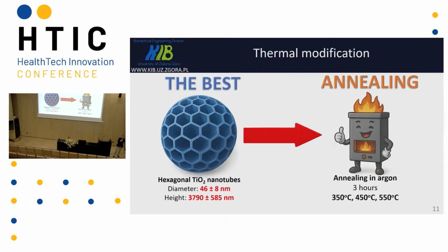I told you that we had to use a thermal modification process. Why? There are a few reasons. Firstly, we want to carry out the transformation from amorphous to crystalline surface, and additionally, we want to avoid fluoride, or make the fluoride disappear in our nanostructure.